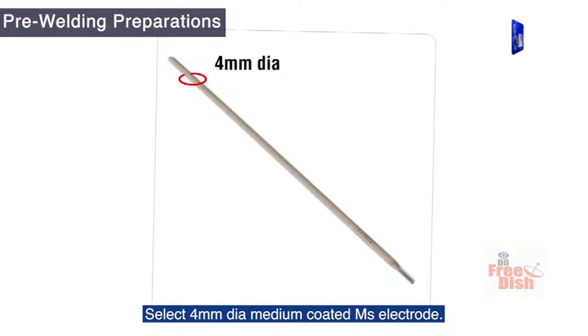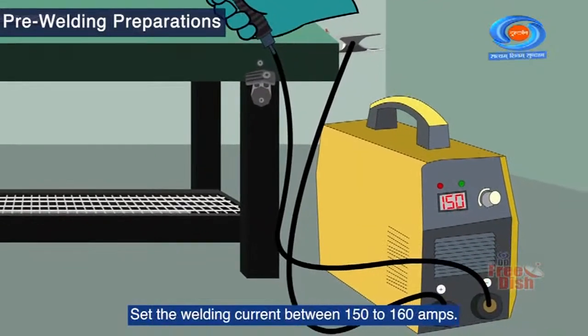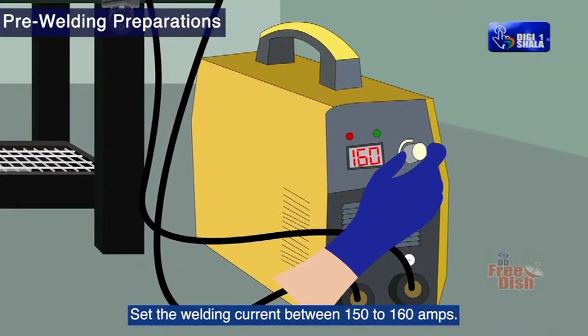Select 4 mm dia medium coated MS electrode. Set the welding current between 150 to 160 amps.